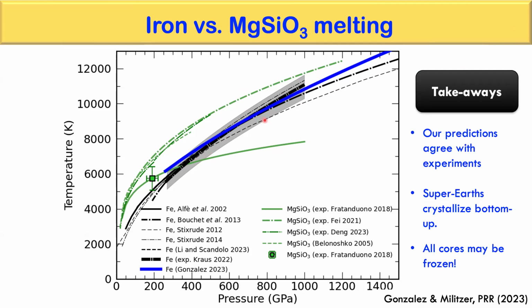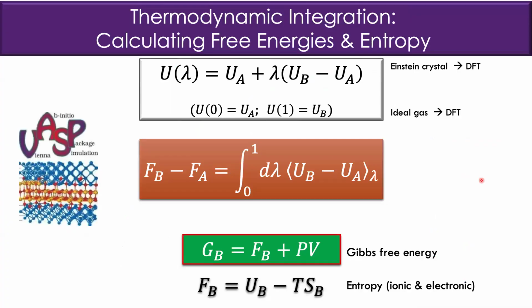And I want to give you the takeaways before we start: our predictions first agree with experiments, the ones I showed you earlier, and that implies that super-Earths start crystallizing from the center, so in a bottom-up scenario, and that all the cores of super-Earths might be frozen. So how did we do this? What we basically do is calculate energies. And we have to calculate free energies. I won't delve into details here. You can ask me later if you're interested.